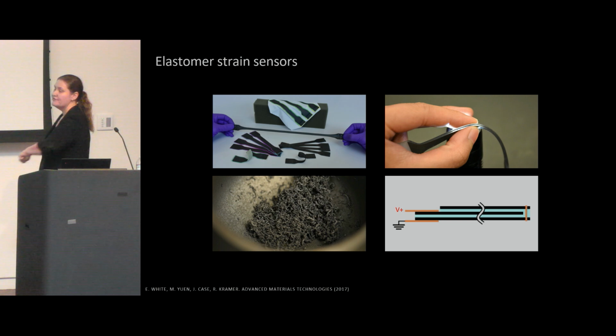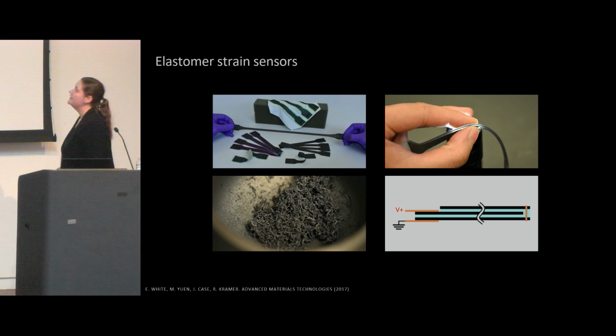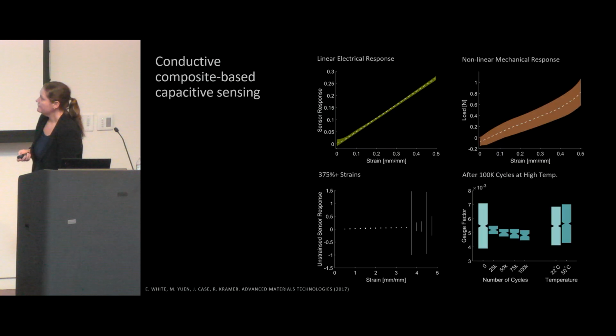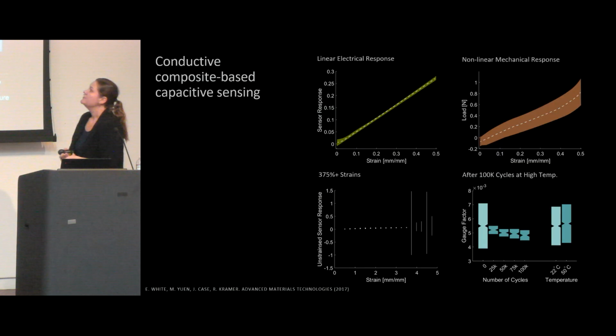And then we can take these flakes and mix them into a pre-cure polymer, and we can rod coat it, make films of it, and cut out these capacitive sensors. So you could use a 3-layer sensor. We make a 5-layer sensor. We just add another dielectric and electrode layer in order to protect the sensor from noise. Okay, so let's look at how these sensors perform.